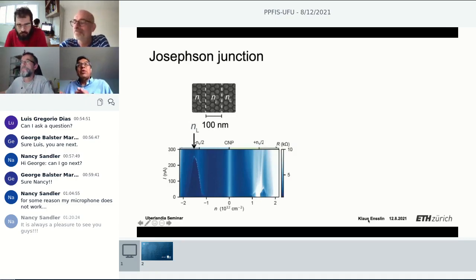Thanks. Just a comment, it's a bit connected with Carlos's question, in that presumably if the mechanism of the superconductivity in the twisted bilayer is electronic, then it will be very sensitive to electric screening. And somehow it is very hard to do in other labs, it seems. Yes, for the superconductivity, there is an experiment by the Efetov group, where they take very thin boron nitride and they get rid of the correlated insulator but not of the superconductivity, which seems to indicate that the electronic correlations are not dominant. But I only know this one experiment by the Efetov group. I don't know the others. All of them use roughly the same thickness of boron nitride. That would be nice if you could.